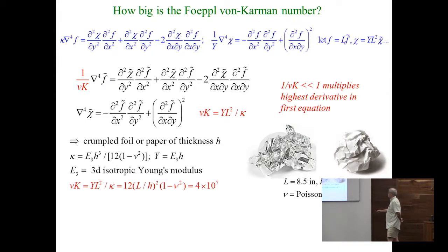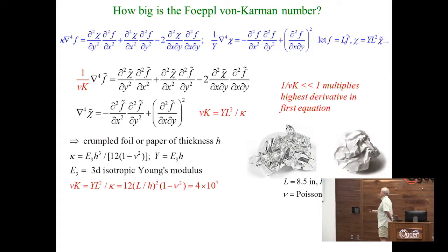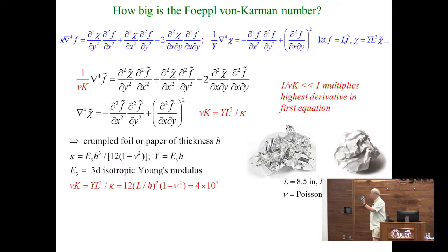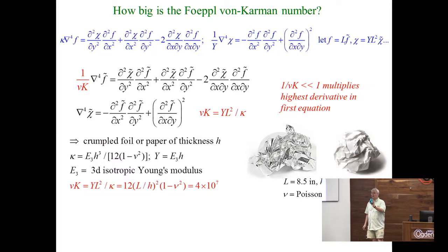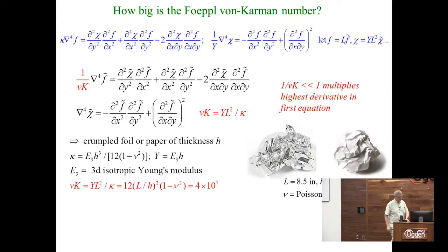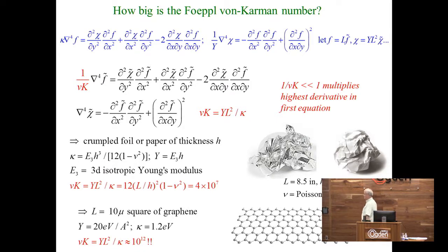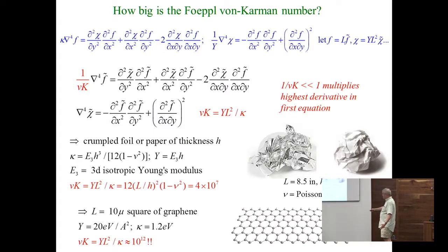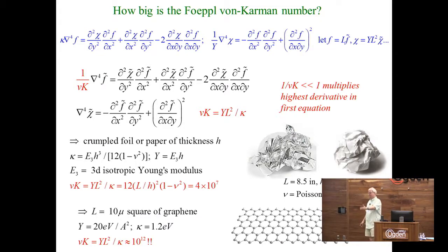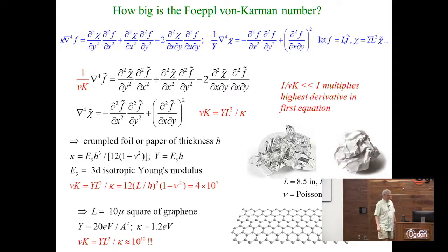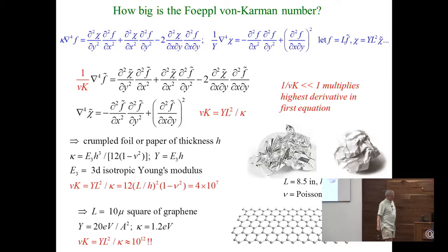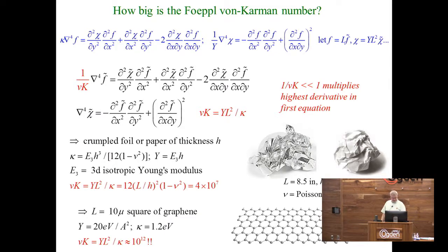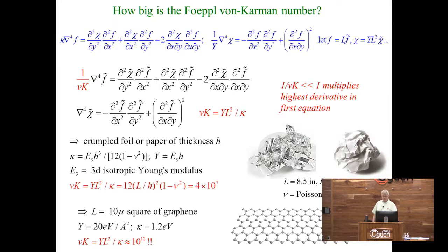This is something called the Poisson ratio. Don't worry about it, it's not important for what I'm going to tell you about. For a piece of paper, a humble piece of paper, this Föppl-von Kármán number is about 10 to the 7th or 10 to the 8th. Good luck doing perturbation theory in powers of 10 to the 7th. Graphene, it's really thin. And these are measured and calculated numbers at 0 temperature for graphene. Its Föppl-von Kármán number is not 10 to the 7th, it's 10 to the 12th. So if you want a nonlinear problem which might have cascade of wrinkles in it when you crumple, not unlike the cascade that Kolmogorov, the great Soviet mathematician, and colleagues postulated for turbulent water flow, this is an interesting and rather promising and challenging area. Any questions so far?